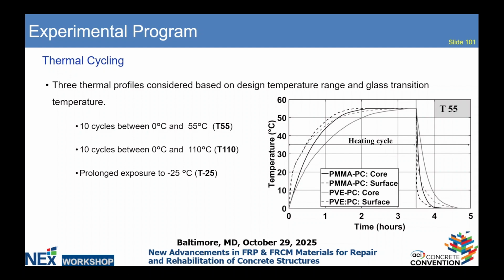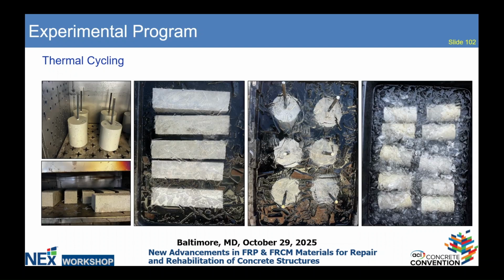On the right side, I have shown one of the thermal cycling, which is T55. A similar cycling was done for 110 degrees Celsius. And for the minus 25 degrees Celsius, no cycling was done. The concrete was tested at minus 25 degrees Celsius itself. For those T55 and T110, the cycling was done, and the residual strength was measured not at 55 degrees Celsius, but at room temperature after exposing to those cycles.